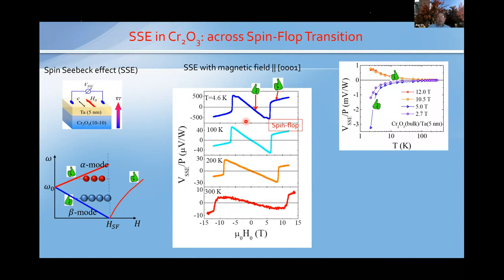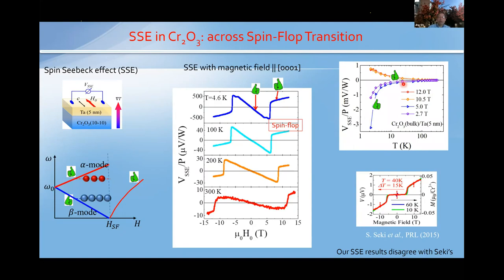Okay, so I should speed up a little bit more. The temperature dependence is showing right here. So let me just quickly show the comparison with the 2015 PRL data on chromia. We concluded differently. We concluded that even below the spin flop transition, we have relatively large spin Seebeck response. So this is consistent with this two magnon branch theoretical model, which does not need any induced moment. Okay, now this is the first part.